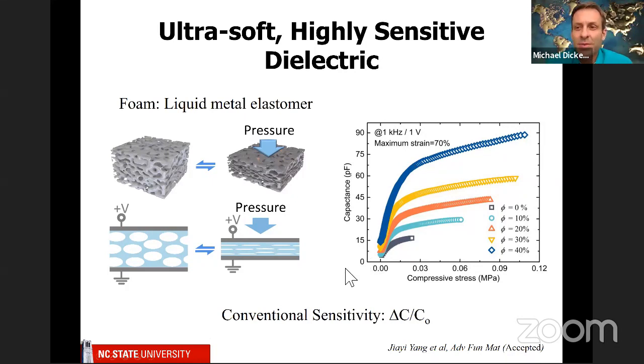Now, I wanted to say something, and I hope this is not too controversial, but there's some literature that uses this definition of sensitivity, which is change in capacitance, so how much this goes up, divided by the initial capacitance. And if you think about this for a few seconds, you realize that there's a little bit of a flaw here. And that is that if you want to make your sensitivity appear very high, you make C0 effectively zero, making your sensitivity appear infinite. But that's really kind of silly because you don't want to have an initial capacitance at zero. You want to have a good initial signal. And you'll see that down here at zero strain, zero stress, we get an enhanced initial signal. So if we use this metric, it doesn't look as good, but in terms of practice, this is actually quite a nice result.